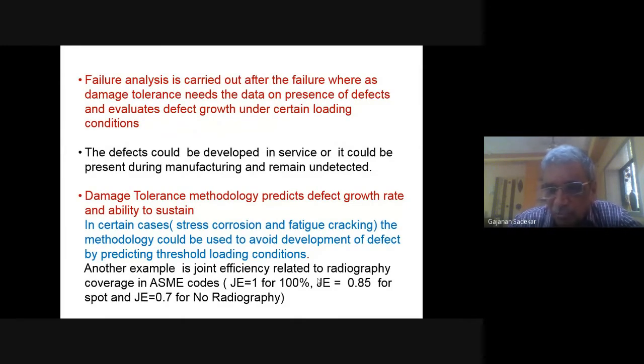Now, what do these numbers 1, 0.85, 0.7 really indicate? This means you are going to use higher thicknesses. Higher weld thickness will come, because if the joint efficiency is 1, the thickness will be a minimum, whereas with joint efficiency 0.7, your thickness will be more by 30%. So you are actually providing for the damage not to occur. So really see this. Somebody can say, oh, this has been put like this. No. And when you say this, you know that the defects which get developed, because you will be welding with a standard methodology, will be very, very minimal. And those defects can be tolerated depending upon the type of radiography.